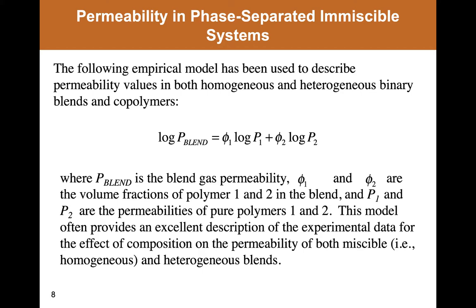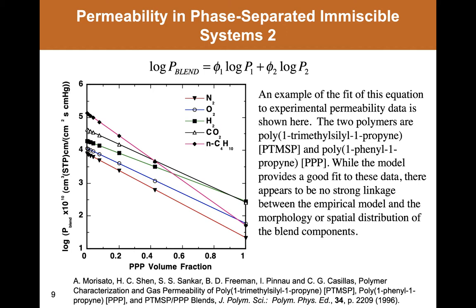And this is showing some data. This is for gas permeation through a phase separated system consisting of two substituted acetylene polymers, poly-1-trimethylsilylpropyne, which we've seen before, and one of its structural relatives, poly-1-phenyl-1-propyne. These materials phase separate from one another, and the permeation properties follow pretty well this particular empirical model.